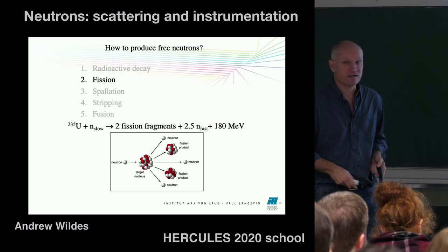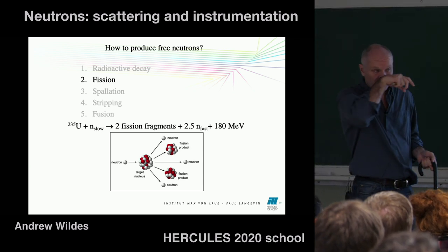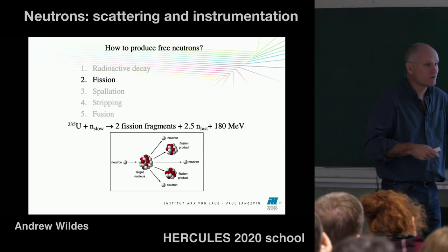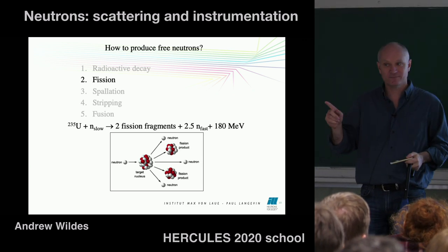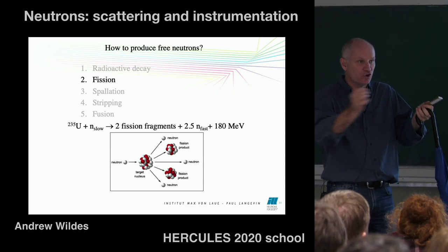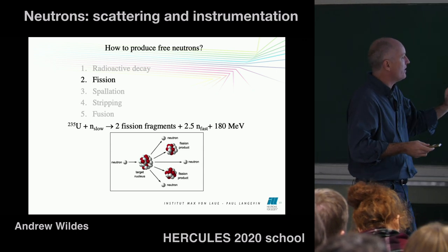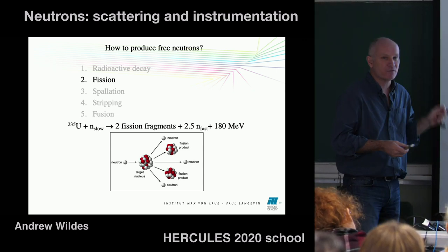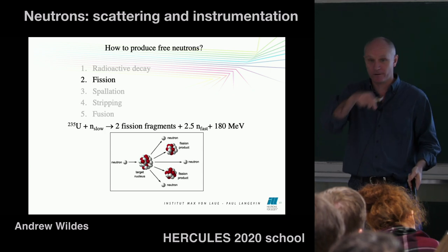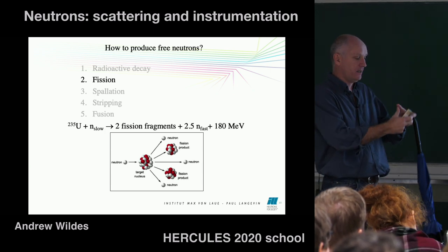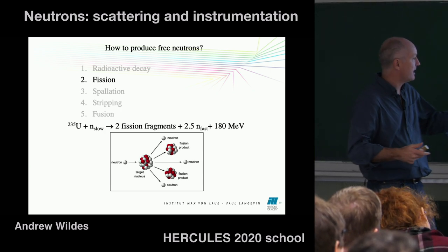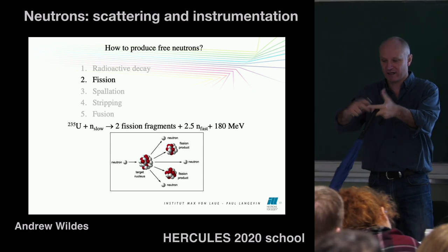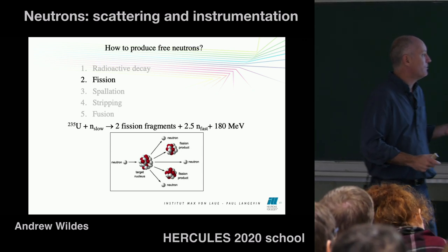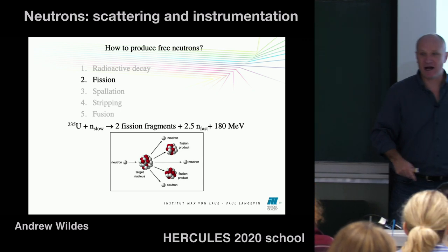In this particular case, it's an isotope of uranium. If that uranium absorbs a neutron, and the neutron has to be slow, this is important. So it has a slow neutron that will come in. There's a reasonably high probability then that the uranium will absorb that neutron. It becomes unstable, and then it will decay. It decays into 2 fission fragments. It spontaneously breaks apart. It produces, on average, about 2.5 neutrons.